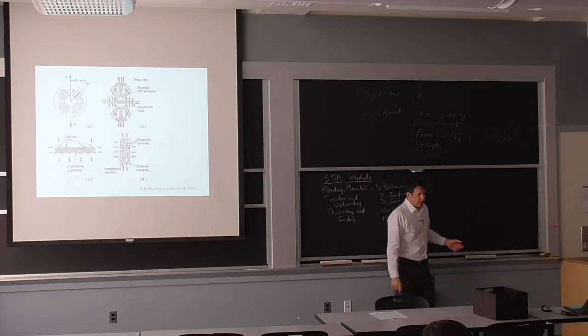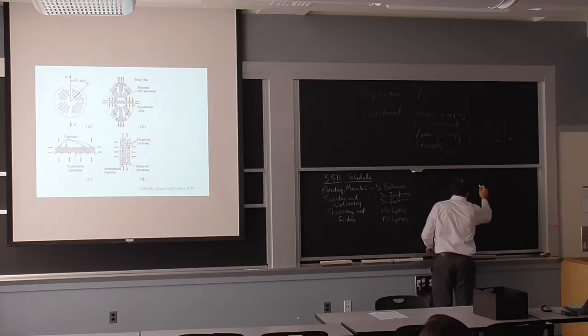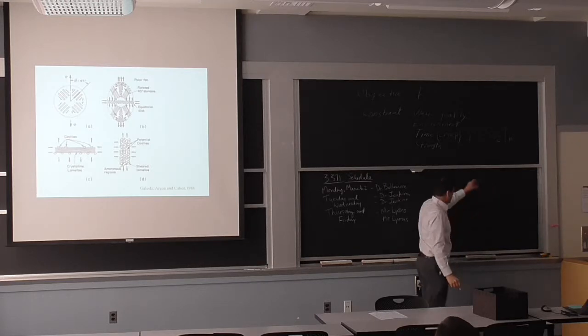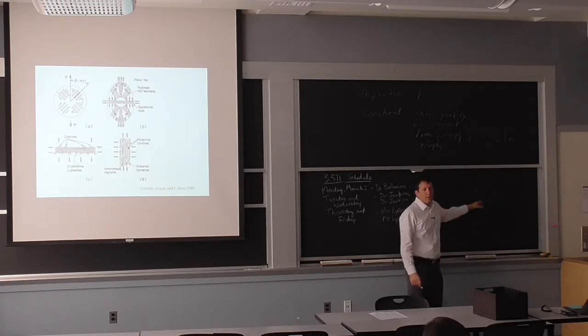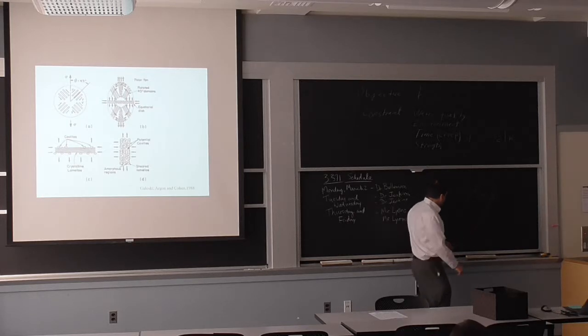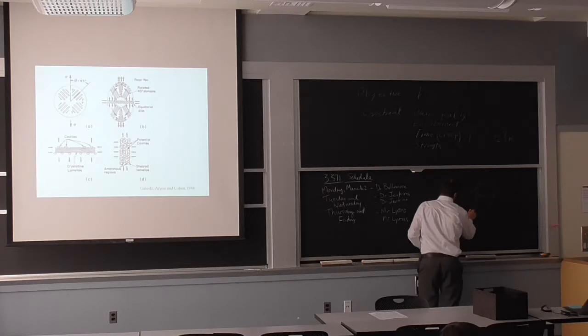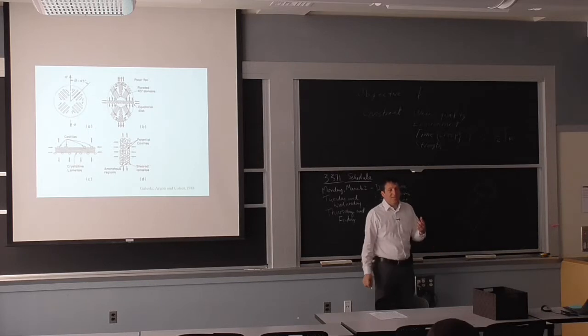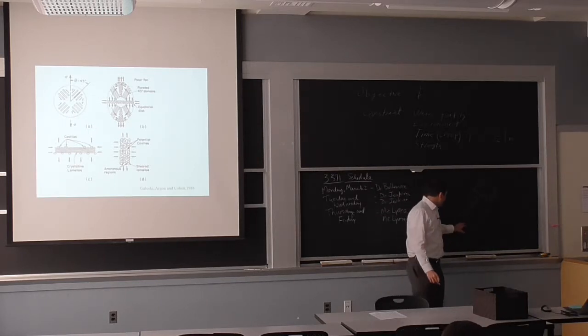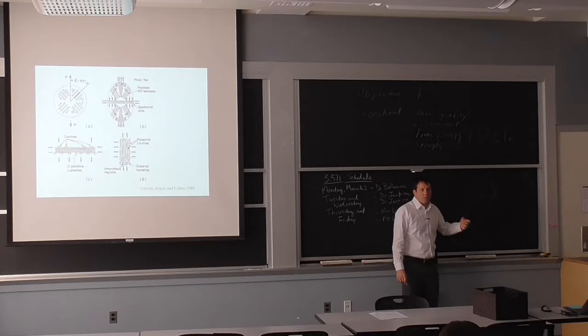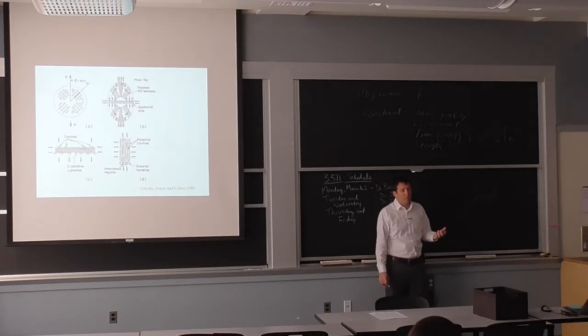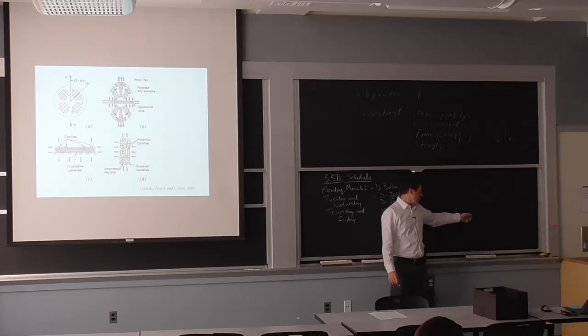The extrusion process, if I have the wall thickness here, is essentially going to create an alignment in this direction. So if I take a coupon here, a strip, and I pull it this way, it's going to be stronger than if I go in the transverse direction. And that itself is a big disadvantage, because this direction is the hoop direction going around. So under just the pressure, you have more stresses in this direction than in this one.